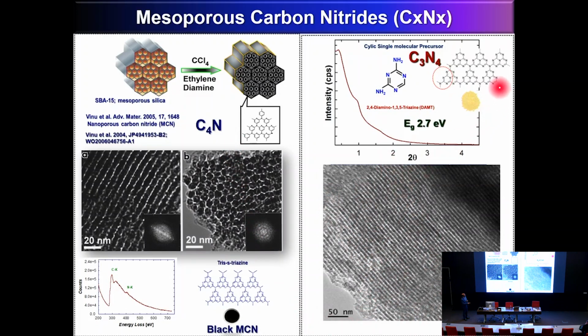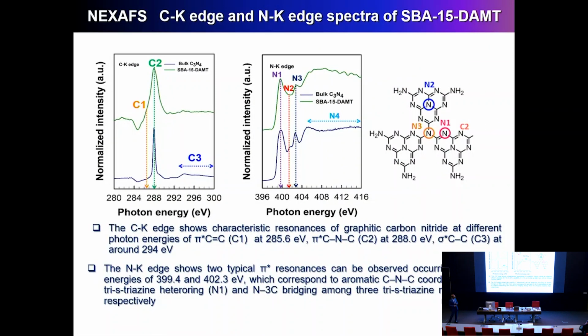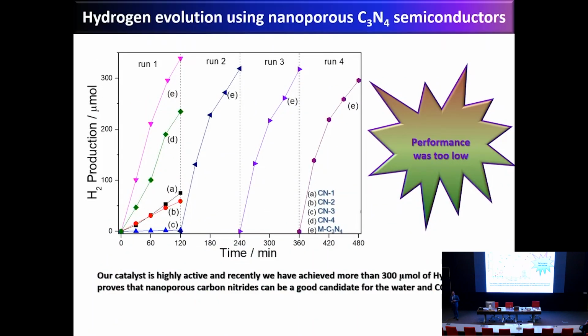And this is C₃N₄, and it's a yellow color, right? And what about its chemical structure? We compare the chemical structure of the material with the bulk carbon nitride C₃N₄. It's almost similar. So that means that the prepared carbon nitride with nanoporous structures with the C₃N₄ stoichiometry has this triazine structure. So what about its performance? The visible light photocatalytic performance. And this is the bulk carbon nitride, and this is our nanoporous carbon nitride with the C₃N₄ stoichiometry. So there is a huge increase in the hydrogen production.